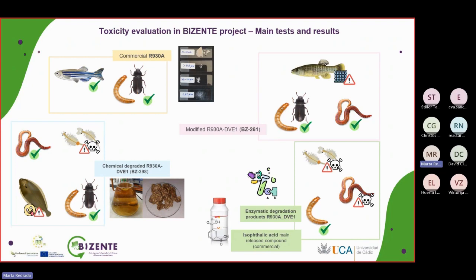For this, we saw that the Tenebrio molitor is fine, but for the worms and the artemias, we could see some deaths when the concentration of isophthalic acid is about 0.5 grams per liter. But the positive result is that in our biodegradation process, the concentration of isophthalic acid is less than that, so there shouldn't be any deaths, and that will be confirmed in the next few weeks.